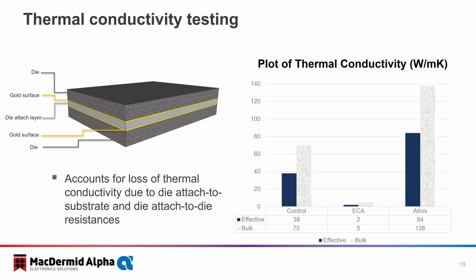Our internal testing delivers effective conductivity. This takes additional surfaces into the calculation and results in the expected thermal performance with a package build. You can view the stacked layers on the left. We see a significant improvement of the Atrox over both the lead solder control and the traditional electrically conductive adhesive. So the reality is these effective thermal conductivity numbers are realistic performances that you will get in your build. And I think that's important.